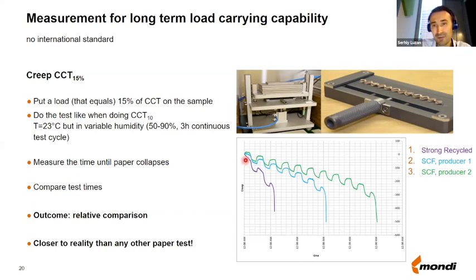On this graph, you can see the behavior of different types of paper in this test. So for instance, the green line and the blue line are showing different semi-chemical flutings, whereas this pink line or violet line is showing you the strong recycled fluting. And you see that there is a clear difference in the number of days that the semi-chemical fluting can hold the load in reference to recycled fluting. And this difference you may not be able to see if you conduct just a simple compression test, because in compression test, this paper may have quite similar performance.